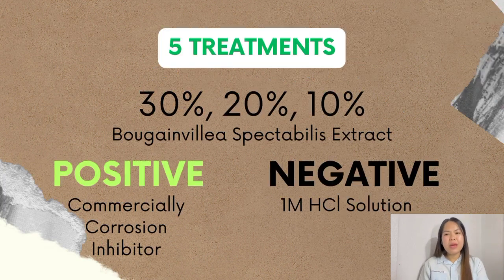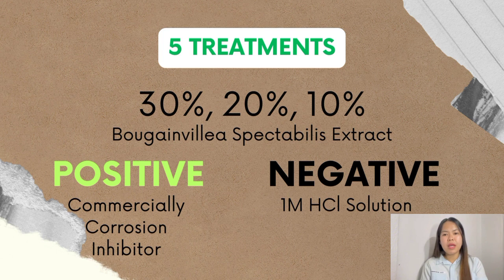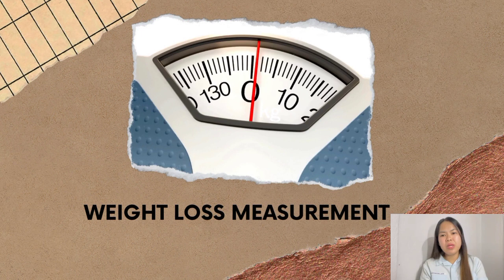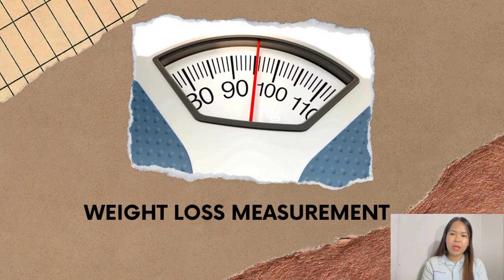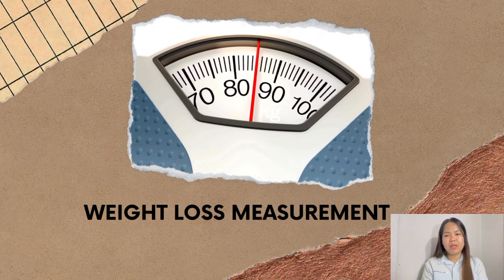We test 5 treatments, including 3 different concentrations of the extract, 10%, 20%, and 30%, mixed with a 1 molar hydrochloric acid solution, a positive control using Turco rust converter, and a negative control using only the 1 molar hydrochloric acid solution. So each treatment is replicated 3 times for reliability. So we assess the corrosion inhibition activity using the weight loss measurement method. So this method provides straightforward and reliable results.